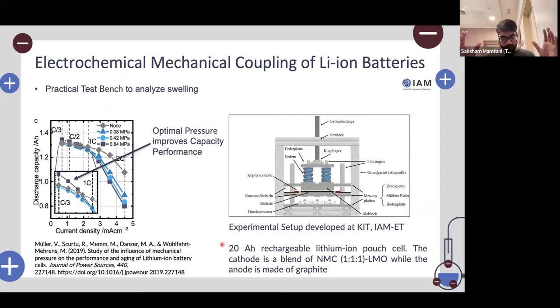So although the topic might be a little bit tricky to understand, it's simple. The impact of pressure on the electrochemical nature of lithium-ion batteries was what I worked on during my 3 months with KIT. Of course, we did not use the graphite and silicon-based anode, but we did use a blended electrode for the cathode side, which again has a similar kind of issue where you might end up swelling the electrodes because the electrode is not a homogeneous material anymore. It has two different materials, having two different properties.